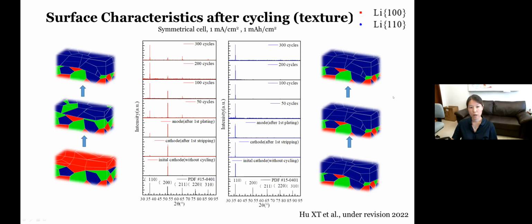Right, and along with cycles, we do see some evolution of the texturing as well. The red one is the lithium-100, the blue one is the lithium-110. As shown here, this is a set of X-ray data, right, taken along with cycles. And this one is the initial cathode, without cycling, and by the way, it's a symmetrical cell.